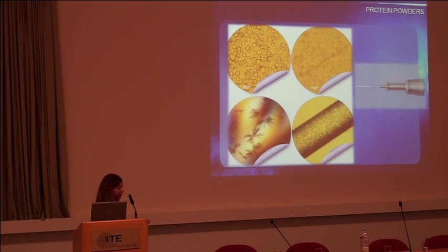We necessitate high crystal packing density in order to have good data. If you have a few crystals, you cannot get reliable data. So you need to centrifuge the glass capillaries prior to data collection.